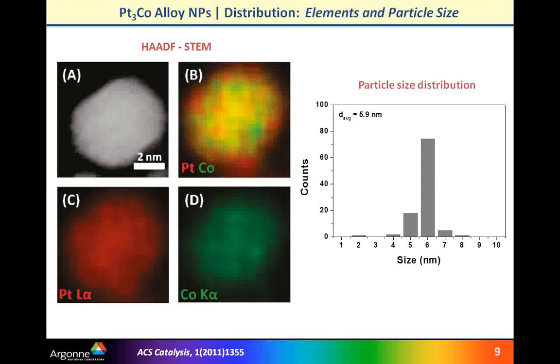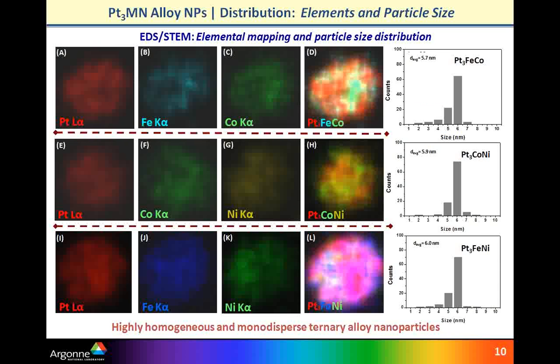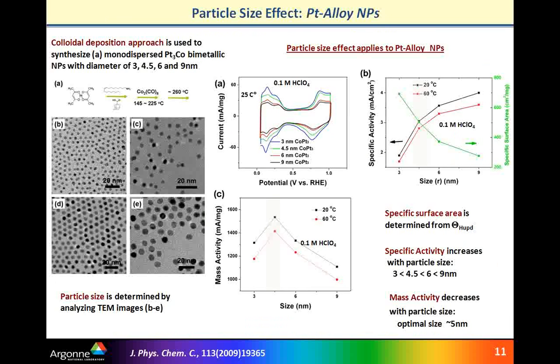this procedure. So not only can bimetallic particles be made, but lately we turned our attention to multimetallic systems and the ability to synthesize ternary alloys. And here is a snapshot of 3 different alloys: platinum iron cobalt, platinum cobalt nickel, and platinum iron nickel. And you can see that in each case we were able to achieve homogeneous distribution of elements, and in addition to that, again, very narrow particle size distribution. So we are very focused on particle size as a very important physical property of the catalyst.